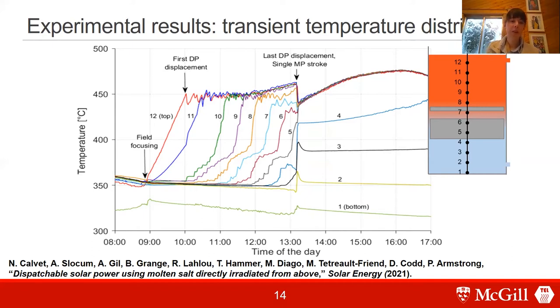Now, one of the big issues here was that we don't actually understand the thermal performance very well of the molten salt, the way that it absorbs and the flow of molten salt inside the tank, so we didn't have any way of predicting what the temperature distribution would be. And so we essentially had some operator sitting there manually controlling the position of the divider plate throughout the day. So this added a lot of complexity to the system. It also added a lot of uncertainty in terms of the design. And so we would like to be able to predict the thermal performance and the temperature distribution in this receiver so we can automate this process and improve the design.